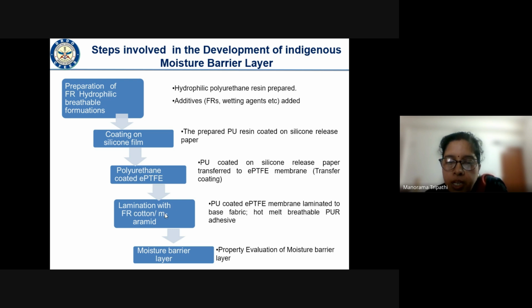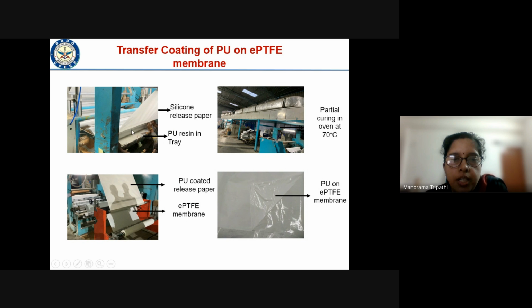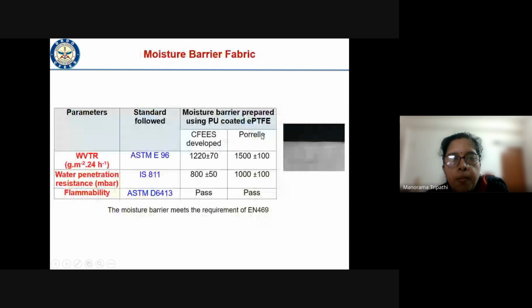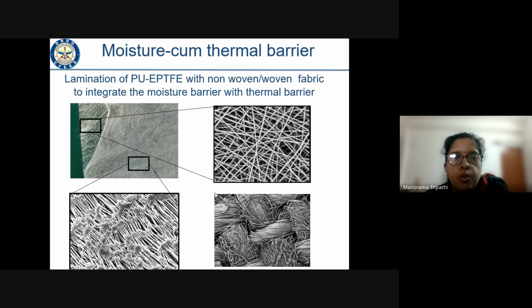And then the moisture barrier layer was made, and this was evaluated for its properties. This is done with a company called RC Chemicals in Pune. And when we compare the CFEES developed moisture barrier with the Porelle that is a commercially available layer, the CFEES developed layer also passed the criteria mentioned in EN 469. So lamination of this PU EPTFE has been done with some non-woven thermal barrier layer to make the moisture cum thermal layer.